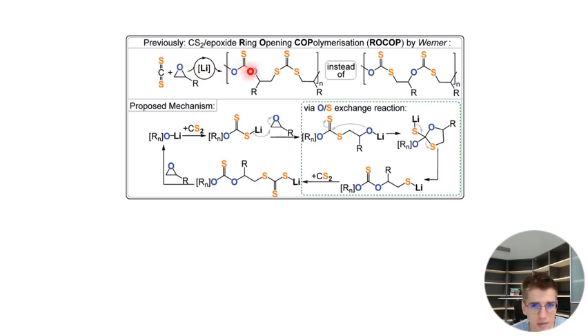However, what they found, instead of one oxygen, two sulfur, one oxygen, two sulfur, is that in 92% selectivity they formed this repeat unit here with two oxygens and one sulfur followed by three sulfurs. So in effect, this oxygen here and that sulfur here switched places in the mechanism. The molecular weights they reached were quite good. I think they reached 90 to 100,000 around that time. The dispersities were okayish, I think 1.7, you have to check. And they rationalized this by the following mechanism.